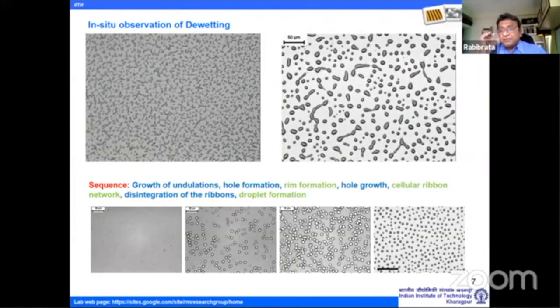And then, for example, a simple application like a spectacle, if you see, and if you want to have 2-3 layers of coating for different functionalities, you are actually adding, to avoid or circumvent the scare of the spontaneous instability, a thickness of a coating which might be few microns, and then you might be ending up having 20 micron of material in front of your glasses. And just now we were talking about reflection and absorption. So please do understand that maybe 10% or 8% of the light that is coming gets absorbed into these layers.